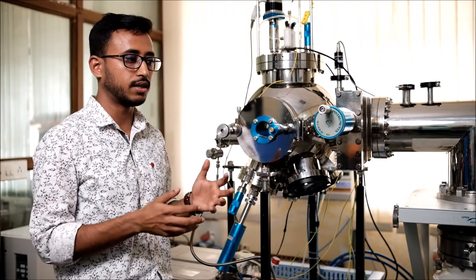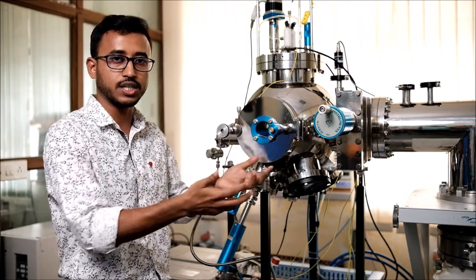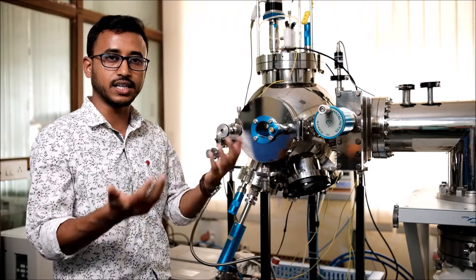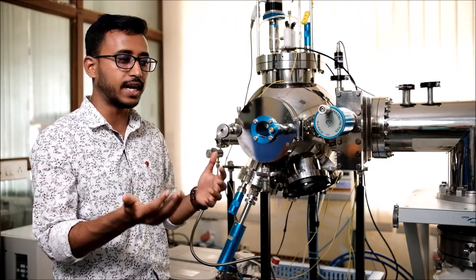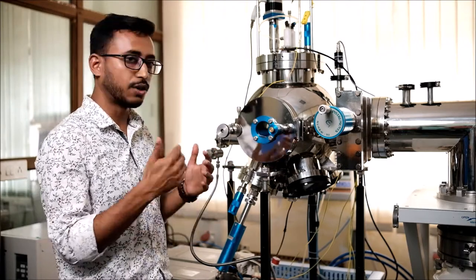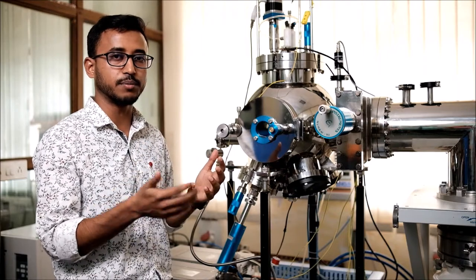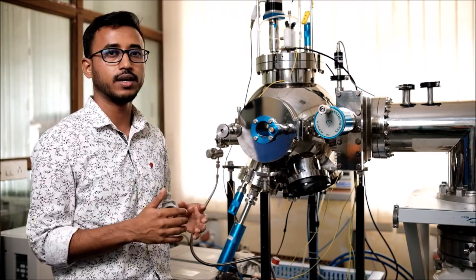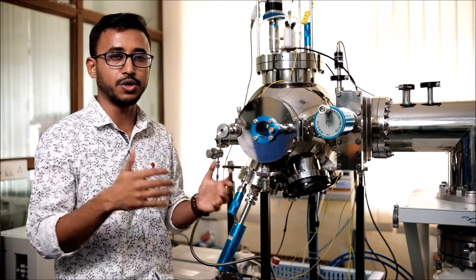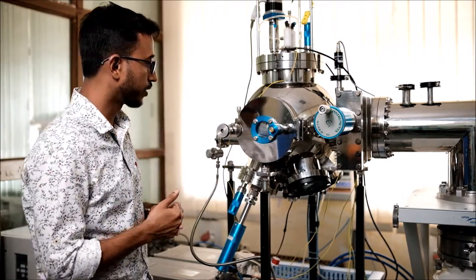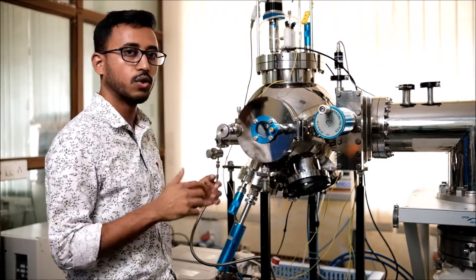Whenever we deposit, the material also deposits onto the crystal and its weight increases, and thus its natural frequency reduces. So by calculating its natural frequency before and after the deposition, we can correlate this parameter to the thickness of the film. With the help of software, we do this.